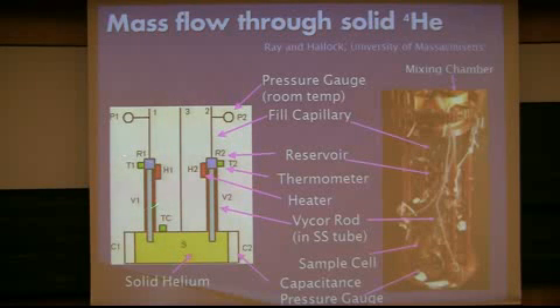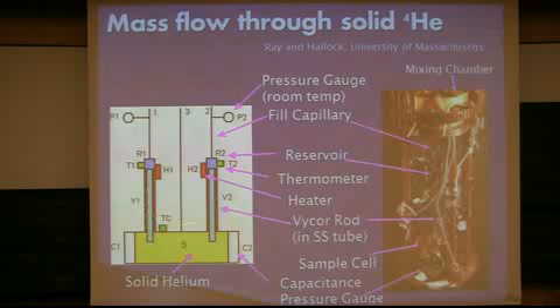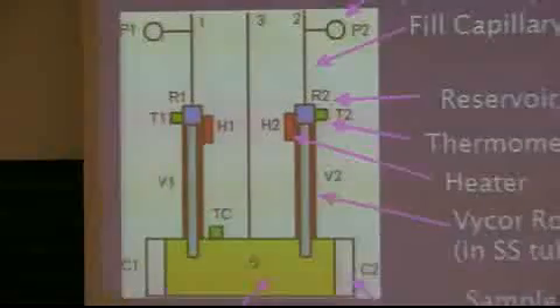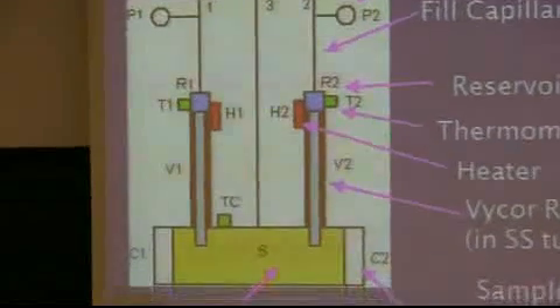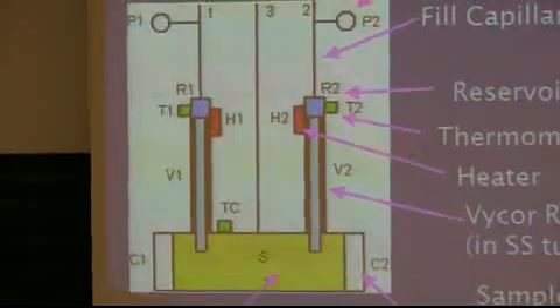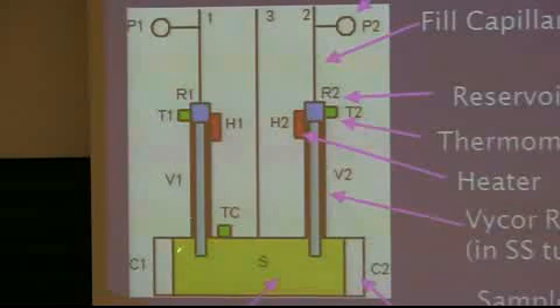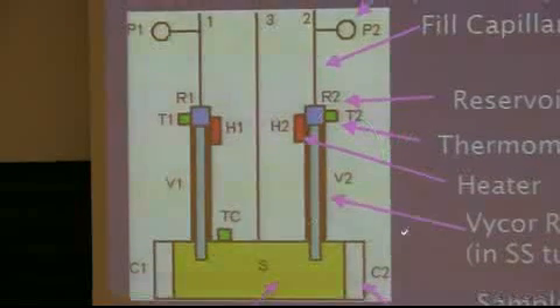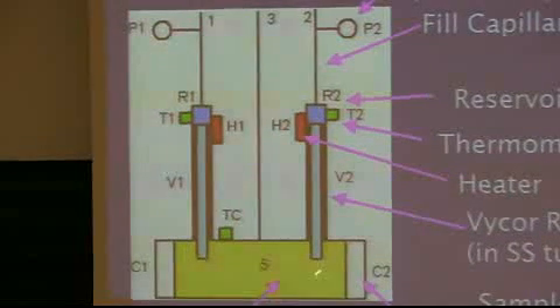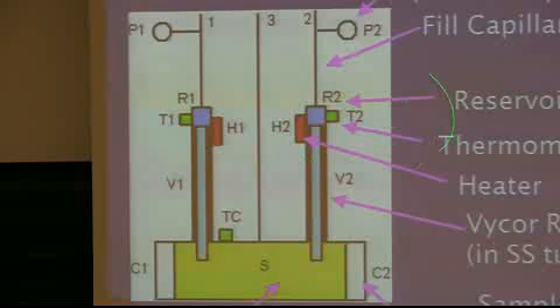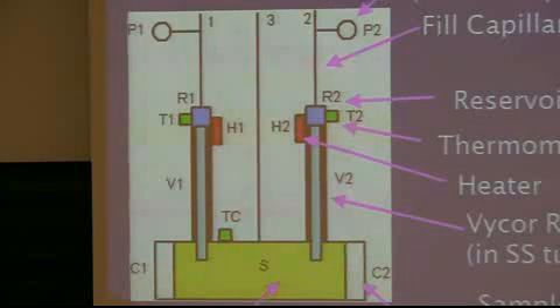However, what they did is they put Vycor glass on both sides of the solid helium, and inside the Vycor glass they have superfluid, and they use the superfluid to pressurize or add atoms from one chamber and measure if there is any flow through this solid helium and change the pressure in the other chamber. Okay? So this is a very clever idea.